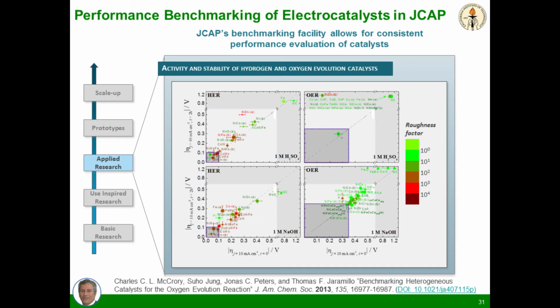Hence, a stable and active catalyst would lie on that 45-degree angle trajectory and be near the origin. And you can see that for the hydrogen evolution catalyst, we already have adequate active systems in both acidic and alkaline media where safe and efficient solar fuels generators can be built. On the other hand, in alkaline media for the oxygen evolution reaction, we have a whole variety of water oxidation catalysts. We still seek, however, to have water oxidation catalysts that would replace the scarce iridium oxide, which is the only stable, earth-abundant or not, metal catalyst for the water oxidation system under acidic conditions.